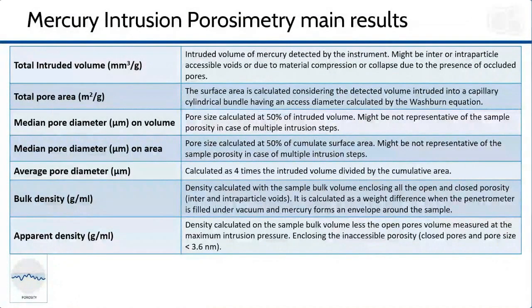Mercury intrusion porosimetry is a well-known technique giving several pieces of information related to material porosity. Mercury intrusion begins under vacuum and can reach very high pressures, up to 414 MPa. Due to these characteristics and to the assumptions related to mercury intrusion, the results should be properly interpreted depending on the material under test. The total intruded volume might be relevant to the interparticle and/or the intraparticle voids in case of powders. Organic material might be compressed, or the structure can collapse under pressure, revealing closed porosity. Finally, the minimum pore size that can be measured is about 3.6 nanometer, below which no information can be achieved and gas adsorption should be used.